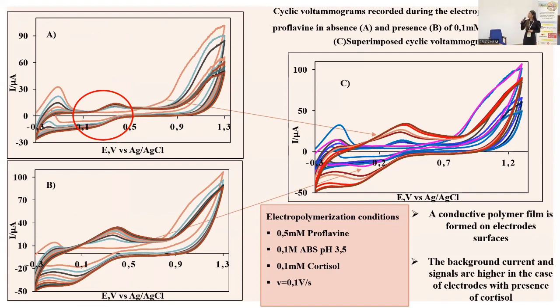The cyclic voltammograms recorded during the electropolymerization of proflavine in absence and presence of cortisol were recorded on pencil graphite electrodes. As you can see, a quasi-reversible redox couple is highlighted by the presence of two peaks. One oxidation peak in the anodic range of potentials at around 0.3 volts, and one reduction peak in the cathodic direction at 0.2 volts. And the fact that these peaks decrease slightly in intensity with increasing number of scans suggests the formation of a conductive polymer film on the surface of the electrode.